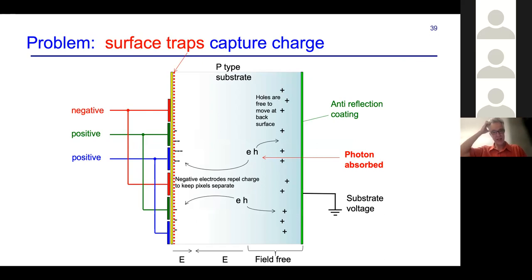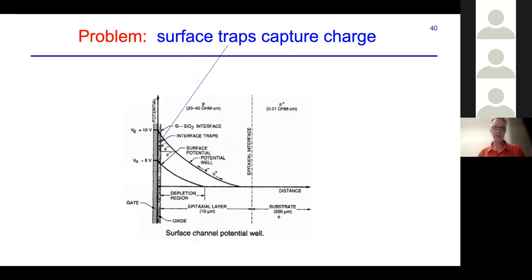Going back to my earlier cartoon of the side view of the chip, we can immediately identify a horrendous problem. And in fact, the inventors, Smith and Boyle, understood this from day one. They understood that there are a large number of defects at the oxide to silicon interface, which create intermediate energy levels in the middle of the band gap, and that electrons get stuck in these traps and left behind as you try to transfer them. And the result is a catastrophe for the charge transfer efficiency.